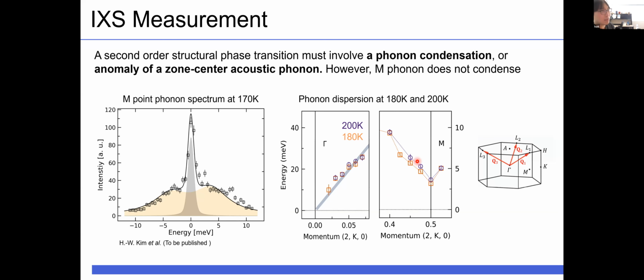What could be another possibility to induce a phase transition? How about the acoustic phonon? When the shape of the unit cell is changing through the phase transition, it can be shown as softening of the zone center acoustic phonon. It was not our original scenario, but it could be. So on the right figure, our phonon dispersion is measured at 200 Kelvin and 180 Kelvin. The slopes are the same at the gamma point. So there is no anomaly in the zone center. So we can say that there is no second order phase transition.